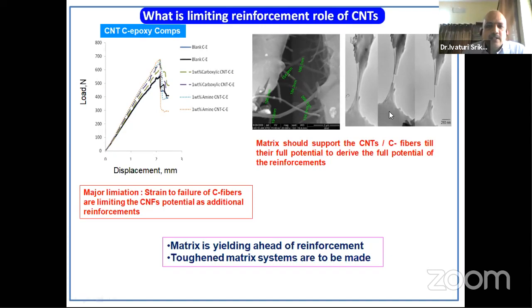So the rule of mixtures says, if you have any reinforcement, say with 2000 MPa strength, and 50% volume of reinforcement is in your composite, then 50% of 2000 means you should get 1000 MPa strength. In the same way, people have calculated the strength of CNT as 80 GPa. If you put in 1% of CNT, you should get around 800 MPa improvement in the strength. So that was the expectation.